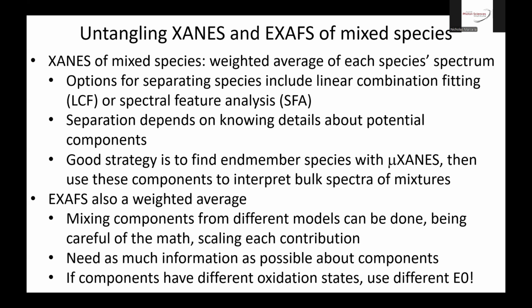So a good strategy is to use microbeam XANES to find end members within a sample of the different components, and then use those components to interpret the bulk spectra. That's been done a number of times for a number of different elements very successfully. And you don't necessarily have to find an absolutely pure spot of one component. But if it's enough to identify what the components are, then you can say, okay, these are the components that are in my mixture, and then I can analyze where they are and how much they are.